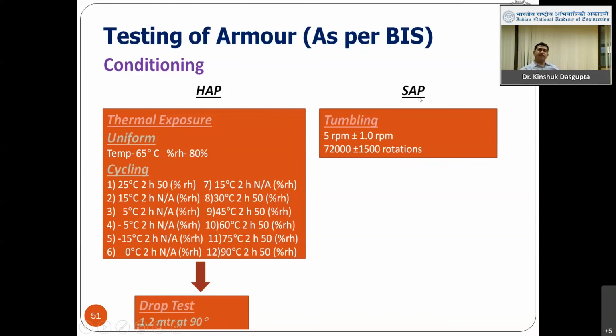Then the SAP, that is the soft armor panel, undergoes tumbling. That means inside a drum there is water, and you rotate the drum with the soft armor panel for 10 days. After that you take both of them and do the drop test. This hard armor panel is dropped from a height, and no crack should be generated, because once a crack is generated, that is a flaw. If the bullet hits there, then it is finished. After all these tests, you have to undergo the ballistic test. So this kind of harsh condition, the jackets are tested under.